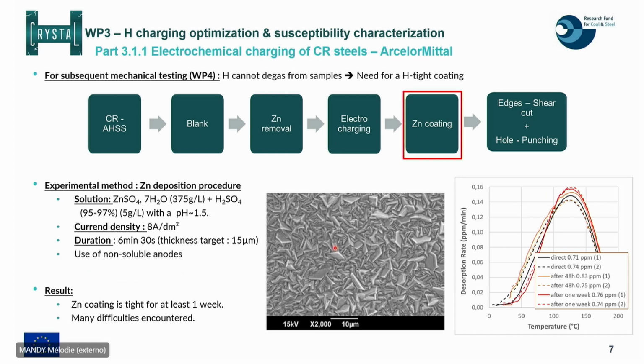Then, as Sílvia told, we also had to zinc coat those materials again in order to impede hydrogen degassing. We want to charge them, but we do not want them to degas too rapidly, because afterwards we wanted to do some mechanical testing, and we also need to transport the samples. For this zinc coating, a specific methodology was developed at ArcelorMittal with a specific solution. It consisted in electrodeposition of zinc to obtain this hydrogen tight coating. The conditions are here. I will not enter into the details, but the result is that the zinc coating developed by ArcelorMittal was proved to be tight to hydrogen diffusion for at least 1 week, which is a sufficient duration for our mechanical test and for the transportations.